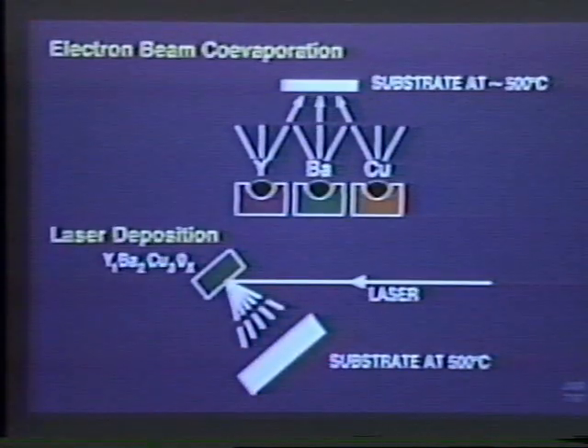In the top there, I show electron beam co-evaporation, which has been used at IBM and Stanford recently with success. It requires a number of evaporation sources, electron beam sources, which give beams of yttrium, barium, and copper, which come together and impinge on a substrate, which is generally held at temperatures, say, about 500 degrees C. Now, that technique is versatile. You can vary the rates of each component separately, but it does need careful control of those rates, and it's a relatively expensive system to set up.